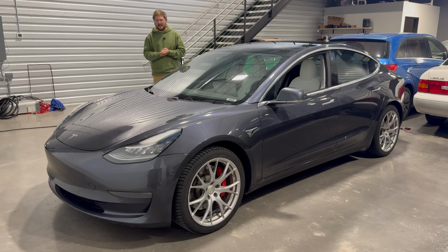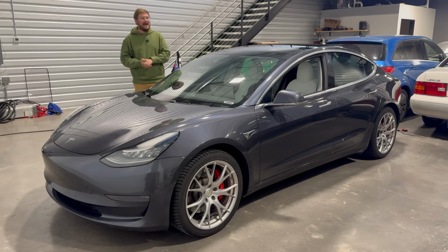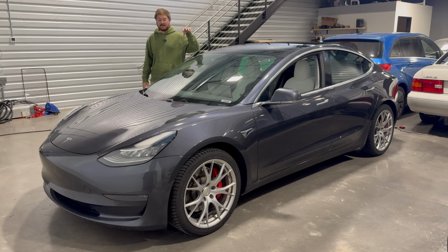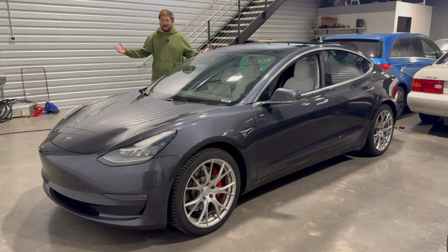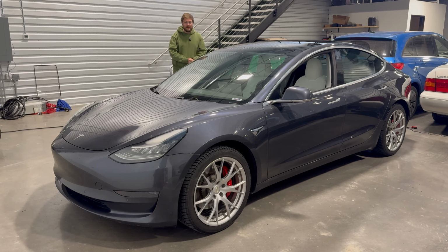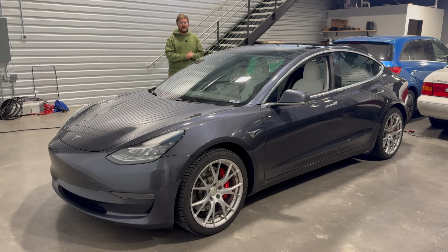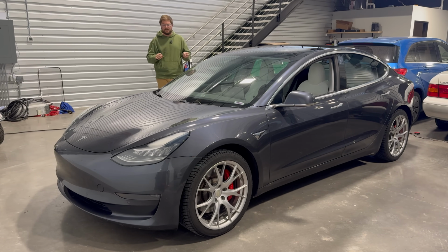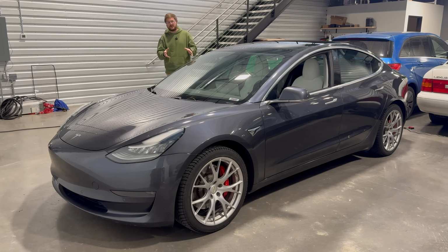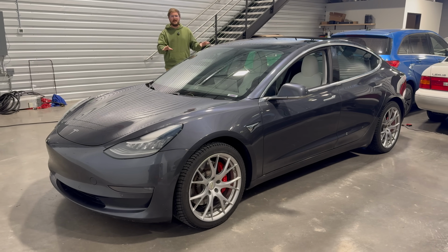If you don't follow me on X, I'll leave that linked below. And so many of our viewers submitted their battery health test results, and many of them with much lower mileage and much newer vehicles had worse scores than this car. Some of that is just a factor of what battery they actually have in their vehicle. My impression is this early Panasonic pack that's in the Model 3s, the 74 kilowatt hour packs, not the updated cell that went into the newer ones, is a really hardy cell. These things last well. They discharge really well. They love to charge fast, especially at low states of charge. And my impression is this cell is pretty great.